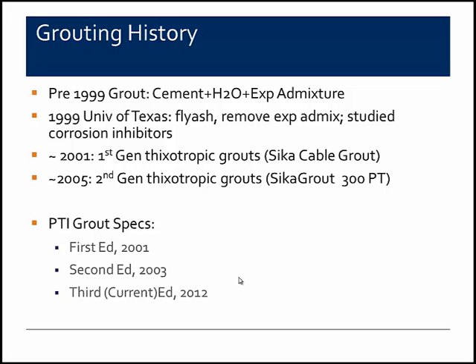So they recommended using fly ash in the grouts. They recommended removing that expanding admixture. And with regard to corrosion inhibitors, the corrosion inhibitors on the market at that time tended to perform less than desired as far as corrosion protection. The issue is related to dosage rate. Corrosion inhibitors are typically dosed based on concrete volumes, and when you introduce them into grout, they may not work as well, and in some cases they could actually accelerate corrosion. So at the time, they recommended against using corrosion inhibitors.